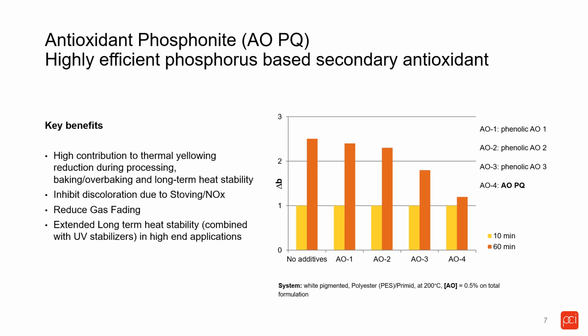And what we see is that at 10 minutes, there is really not much difference between the different antioxidants when it comes to the yellowing. However, when you go to 60 minutes, and very often we call this an overbaking test, and there are two ways to do an overbaking test, either by increasing the temperature of your oven or by extending the time of the curing, we can see that there is quite a significant difference in the yellowing between the different antioxidants.